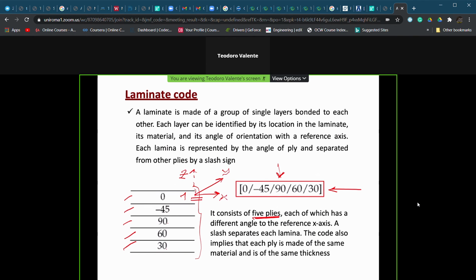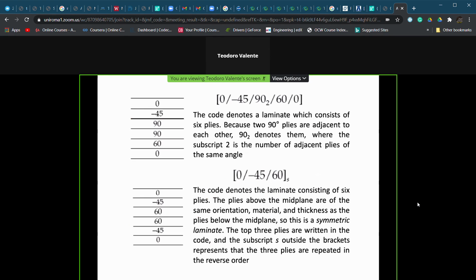When we move to minus 45, this means the fibers are aligned with respect to the X direction at minus 45 degrees. Then we have orthogonal, that is 90. Then we have 60 degrees. Then we have 30 degrees. And you see, in this case, when we, for example, think to apply the load in this direction, just to make an example, this lamina will show on this direction different properties in terms of response with respect to minus 45 or 90, because in this case, let me say, stresses are oriented through a principal direction. In these other cases, no, and so we need the matrix transformation and the necessity to use also the theta angle as we defined before.